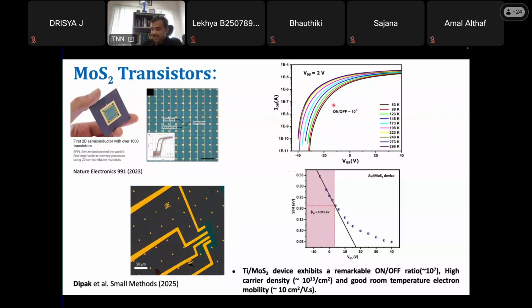So what we found is that in terms of semiconductor metrics, the quality, the on-off ratio is quite high, and the performance is quite nice, but this performance comes with a titanium contact. So a titanium MoS2 contact will exhibit a remarkable on-off ratio, high carrier mobility, high carrier density, and with silicon dioxide, a reasonably good mobility too. The mobility of the material depends completely on the dielectric you use. So basically, it's also quite nice.